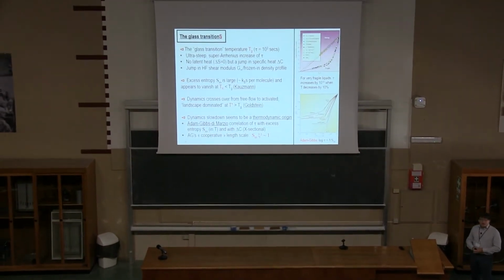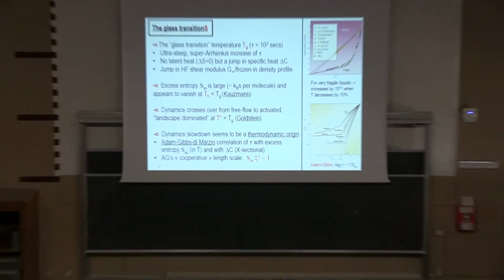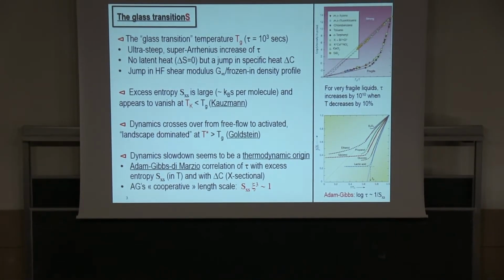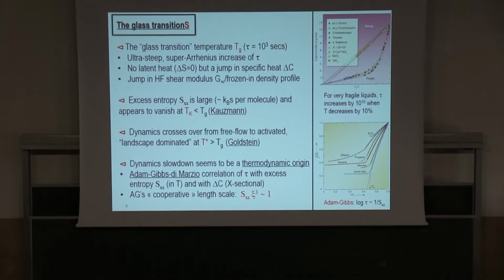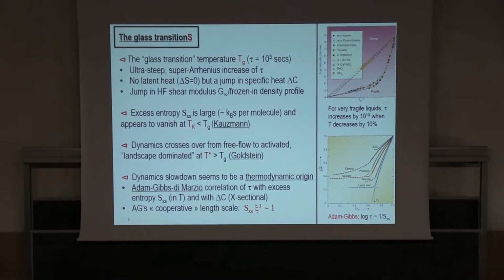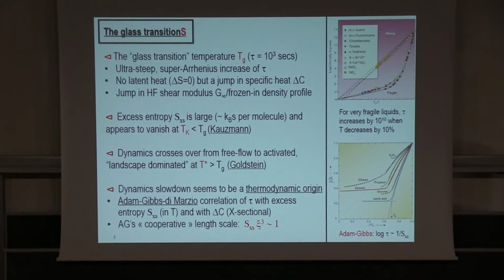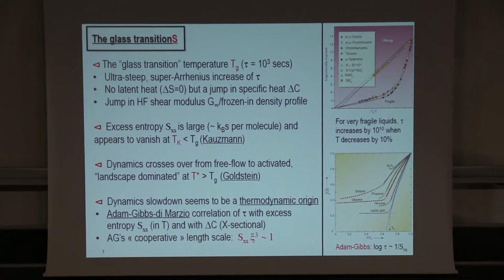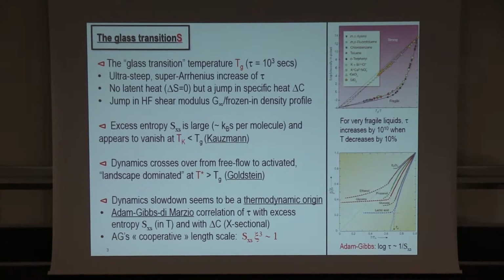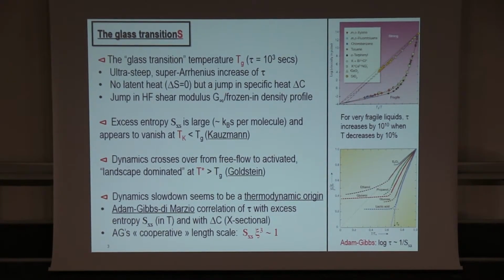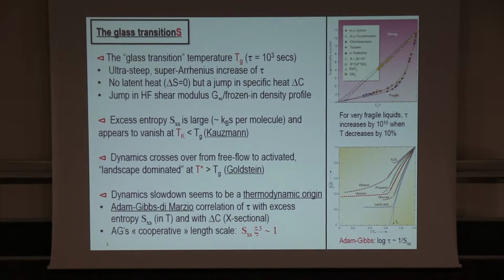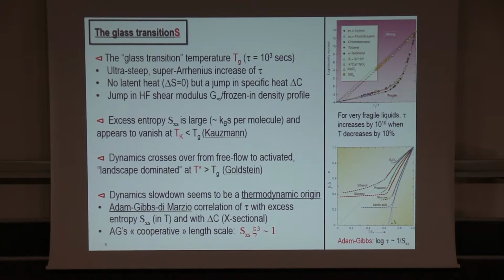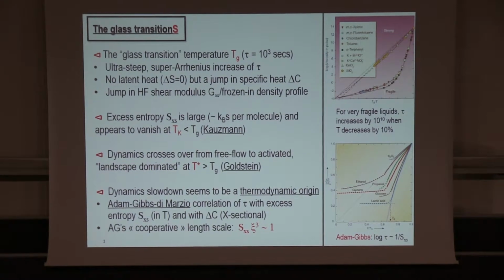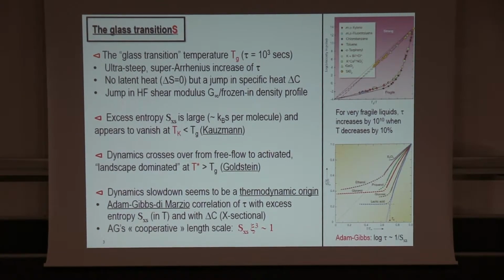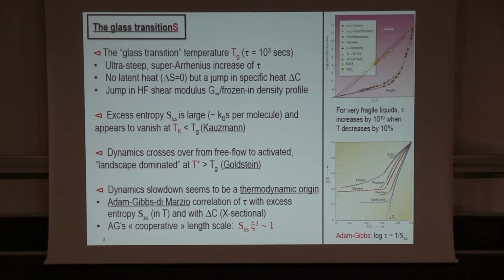So I'm going to show curves that are so well known that they become corny now, but I just want to remind you of the basic phenomenology of glasses. Actually, there are different glass transition temperatures already at the time, at least three. So the traditional glass transition temperature, where the relaxation time reaches an arbitrary number, 1,000 seconds. And what was known is that the relaxation time increases extremely fast close to Tg, actually super Arrhenius.